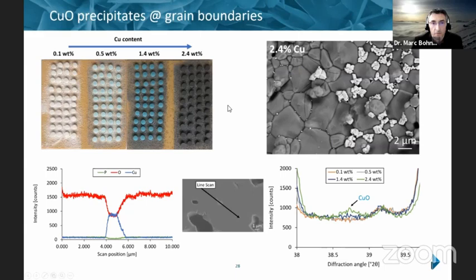These are results with the copper doping. You can see the nice change of color when you add a bit more copper. And if you add more, then you get this black color, which is typical for copper oxide. And actually you can see that it has segregated at the grain boundary. And you can also confirm the presence by EDX or by X-ray diffraction.